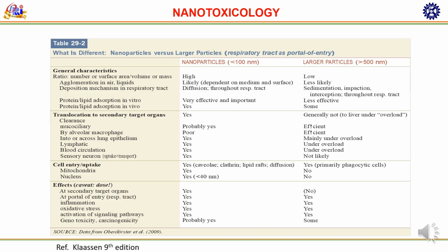Here are the different types of differences. What is the difference between nanoparticles versus larger particles? You can see here the ratio characteristic. Nanoparticles have a very high surface-to-volume ratio that makes them more reactive and allows them to interact more strongly with biomolecules. Larger particles have a much lower ratio, making them less reactive. Agglomeration: nanoparticles tend to clump together depending on the medium and surface chemistry. This changes their effective size and toxicity. Larger particles are less likely to agglomerate.